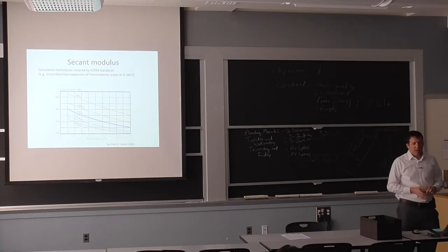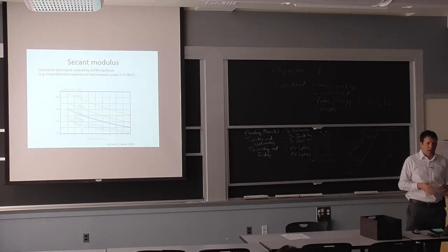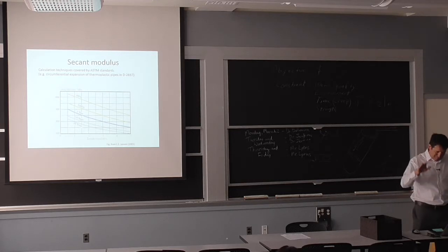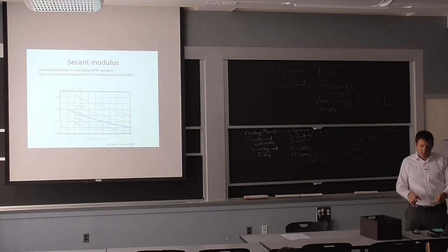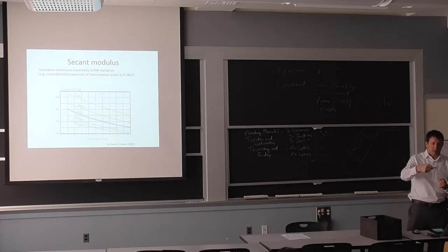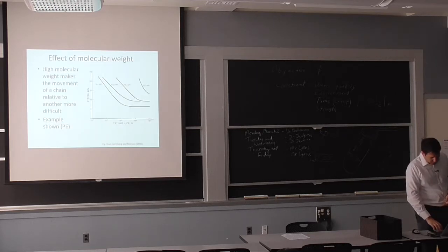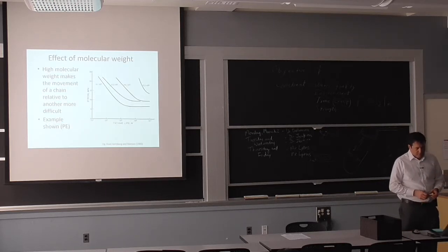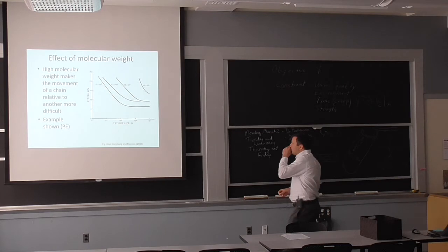So there are very specific techniques if you're going to actually design for the polymer to be used long term. But the main item here is lowering the capacity and not relying at all on the result from just a tensile test in the lab. These are all tests that keep track of how the specimen elongates over time. That's what dictates this design here. So one example of the effect of the molecular weight here on the polyethylene.